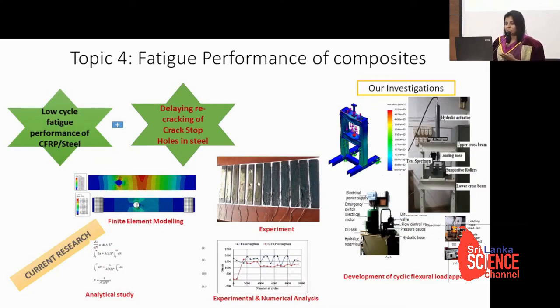In this regard, we need a fatigue load testing apparatus. We thought to purchase one, but the cost is more than 10 million rupees. So we thought, okay, we will design it. First, we developed the apparatus after thorough exploration of existing systems. Then we did finite element simulations and identified critical sections and conditions at the interface. Then we could develop a flexural fatigue loading apparatus. We spent only 550,000 rupees. It's very cheap, and it works very well.